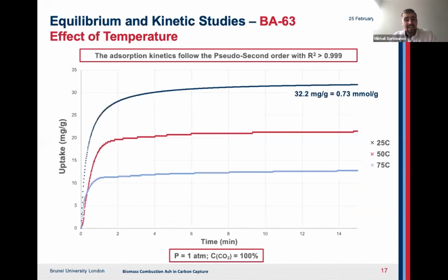Having extensively discussed the characterization of the materials, let's now talk about the experiments, the equilibrium and the kinetic studies that we have carried out. So despite the minuscule surface area, our waste-derived and unactivated carbon has a respectable capture capacity of 0.73 millimole per gram under atmospheric pressure and room temperature, whereas the benchmark for post-combustion adsorbents is 2 millimole per gram at the same conditions, with these specific surface areas for commercial activated carbons or zeolites being much larger.